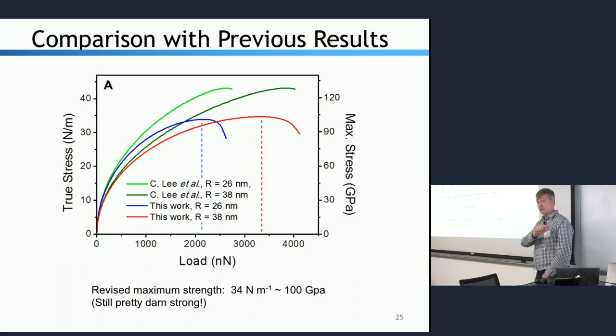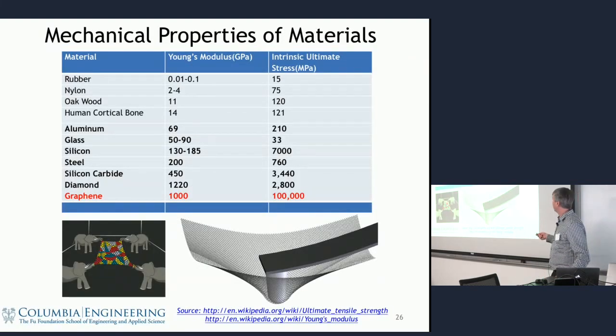That is not correct. The experiment is correct, but the interpretation is based on a model that was too simple. This more sophisticated model going out to higher order terms suggests that 100 gigapascals is a better value. Still, again, that's a heck of a lot stronger than anything else. So it's a pretty amazing material.